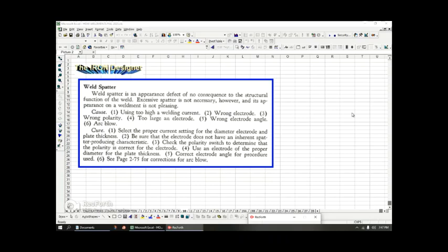to be strong. It may be porosity, or you're going to have concave. You might even be burning the base metal away and spattering the base material. You might have to do a second pass to refill in and grind out the improper weld and then do a second pass on the weld. So excessive current might logically sound like, well, if a little is good, more is better, but it's counterintuitive. You need just to have the correct amount of current, neither too little nor too much.